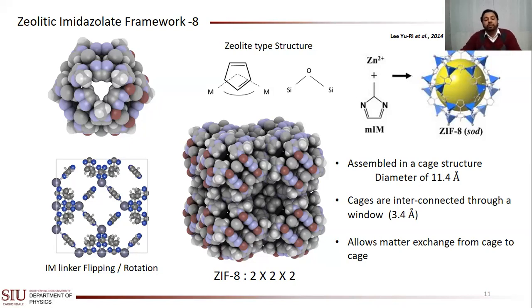This is one of the characteristics that I was actually investigating using adsorption, so that some of the materials or some of the gases that we introduced into the ZIF-8 actually trigger this rotation of the ZIF-8, and the material actually went into the structure. This is not happening in a discrete way. It happens in a gradual change of angle, and it depends on the pressure of the gas.